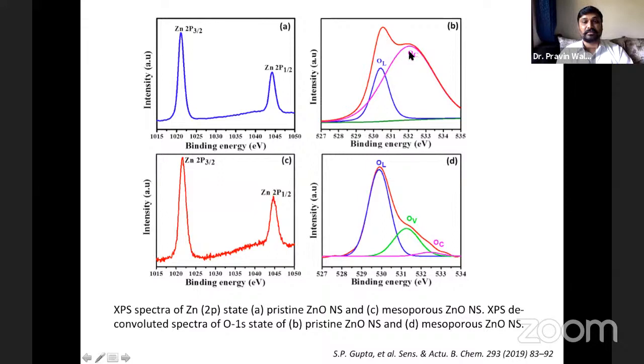So this is lattice oxygen, and this is chemisorbed oxygen. But if you anneal it at a particular temperature and introduce the pores in that particular sheet, you observe that this is the lattice oxygen. And here you see chemisorbed oxygen is quite high in this case, but here chemisorbed oxygen is drastically reduced, and we have found there is an oxygen vacancy peak here. So an oxygen vacancy peak in this has been observed. That means after annealing, you have reduced the adsorbed oxygen content as well as the oxygen content in that, and the pores have been formed.